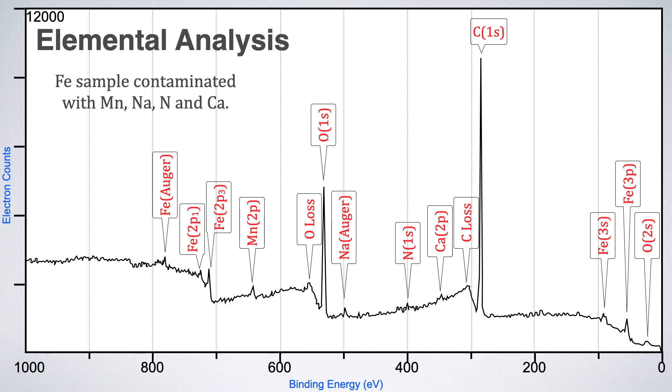The formula for the concentration of any component X can be given as Cx equals fraction of Nx to the sum of Ni where N is the number of electrons which is given by intensity I divided by sensitivity factor S for each electron because each electron is not equally sensitive to the cross section of the instrument. In the graph, peak area of important components are shown here.